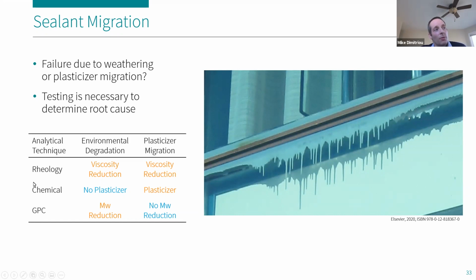But by performing a combination of two additional chemical analyses, you can back out what the governing root cause is. So by performing chemical analysis to search for plasticizers, if you're able to show the lack of plasticizers in this material, that is an indication that there is possibly no plasticizer migration happening. And concurrently, if that's the case, what is likely causing an increase in flowability is a reduction in molecular weight. This comes back to what Erin was talking about earlier with regards to the length of polymer chains.